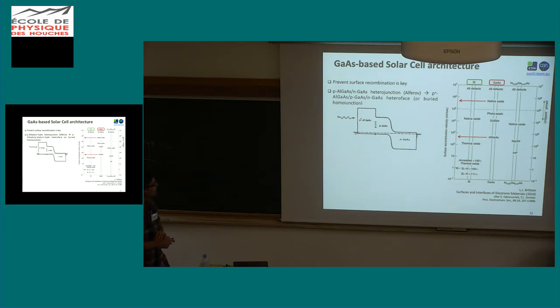So that's why the first heterostructure that was proposed was this heterojunction with this p-type AlGaAs front window layer, and then the PN junction for the gallium arsenide, because here you have the majority of the recombination events, the creation of electron-hole pairs, and is where you really want to prevent surface recombination.